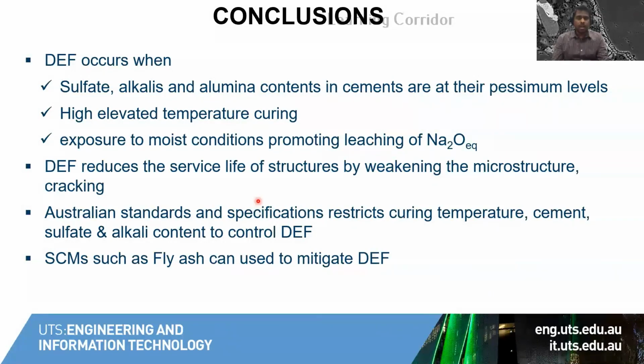So we can avoid, or reduce the impact of, delayed ettringite formation by putting restrictions on heat curing temperature, or restricting the sulfate and alkali content in the cements, or we can use SCMs, supplementary cementitious materials like fly ash, to mitigate delayed ettringite formation.